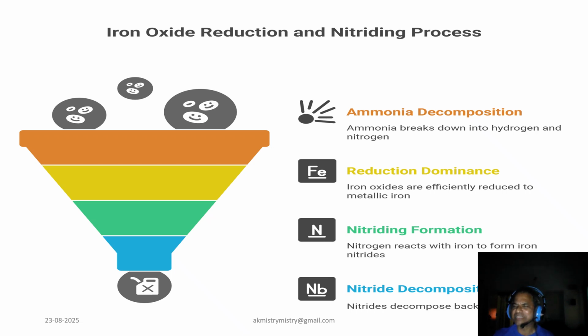Following this, we achieve reduction dominance. The iron oxides are efficiently reduced to metallic iron by the hydrogen. Crucially, nitriding formation occurs next. Here, nitrogen released from ammonia decomposition reacts with iron to form iron nitrides. Lastly, we have nitride decomposition. These nitrides can then decompose back to metallic iron, demonstrating a dynamic and multifaceted process.